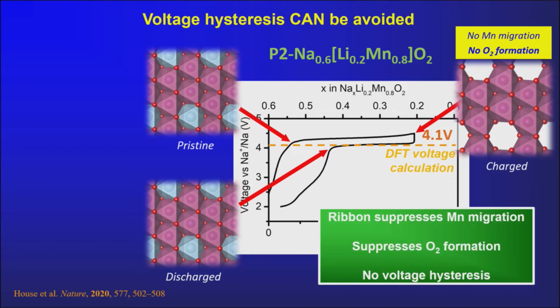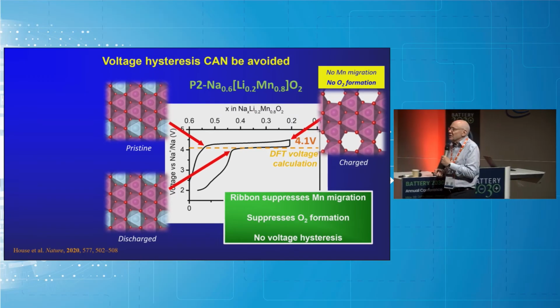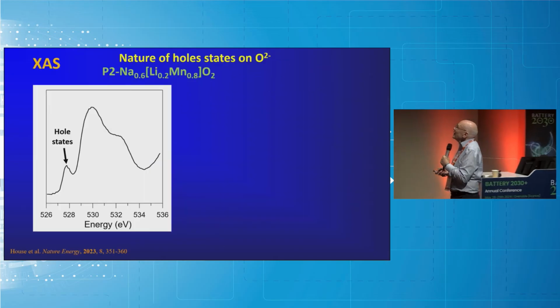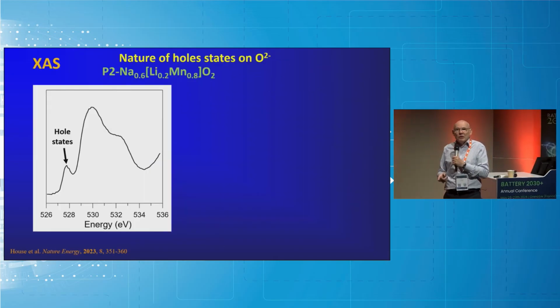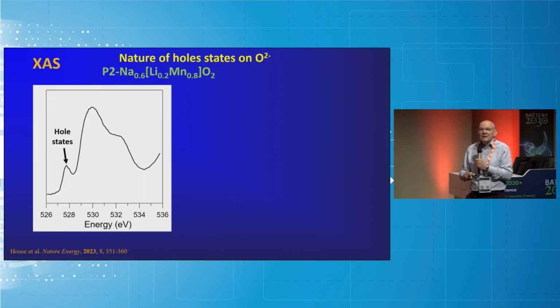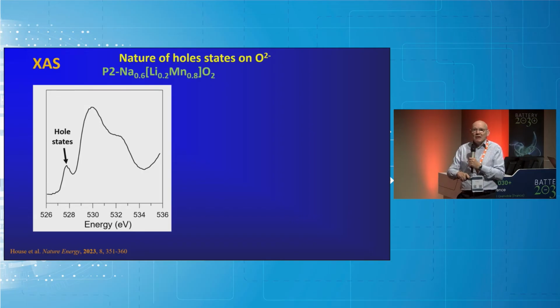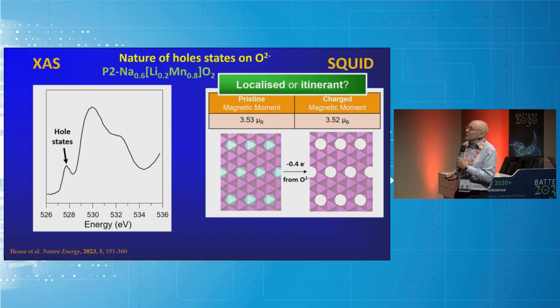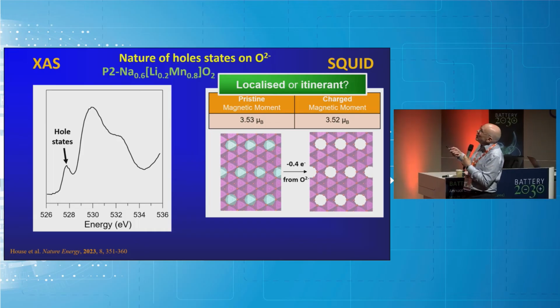So if you don't have the honeycomb structure, you can suppress the formation of voids, and therefore you can suppress O2 formation. And you're getting true oxygen redox. You're taking electrons off oxide ions like you can for transition metal ions, without anything happening to the oxide ions apart from losing electrons. And here's this compound again.